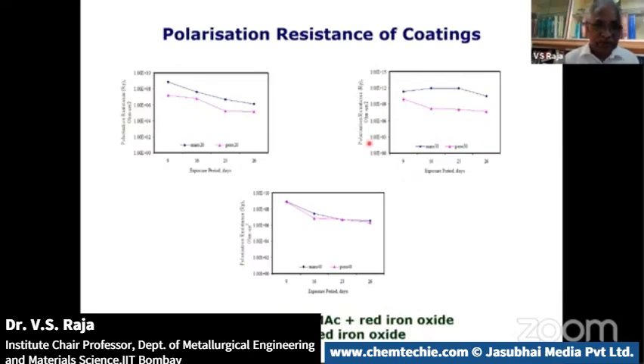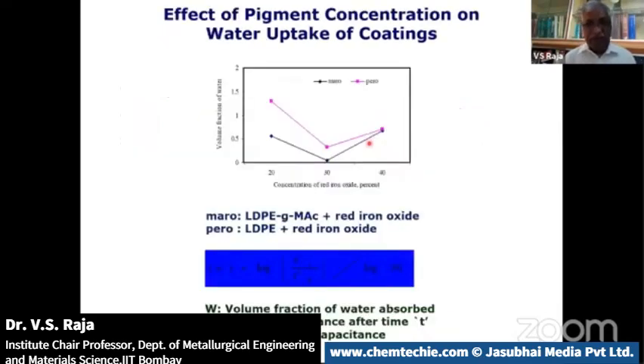Pigments are being added to this particular coating. Into that, again, you can determine the amount of water that is getting permeated, right? We can do this kind of thing. You can see that, in fact, it's very interesting. The water permeation in this coating changes with the pigment concentration. At this concentration of pigment, the water permeation becomes the least, and then you can start increasing.